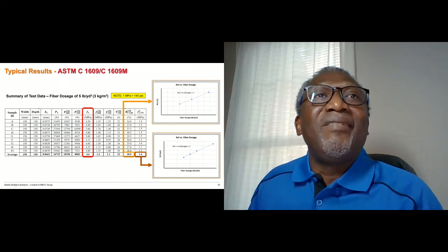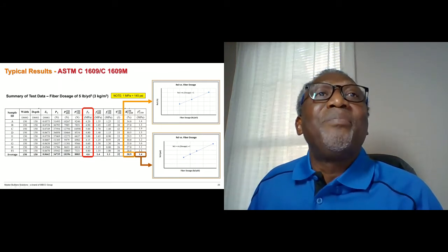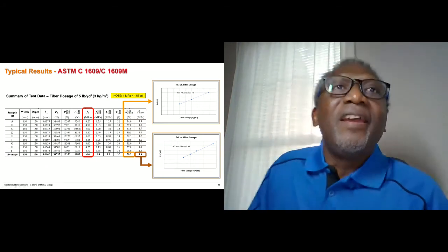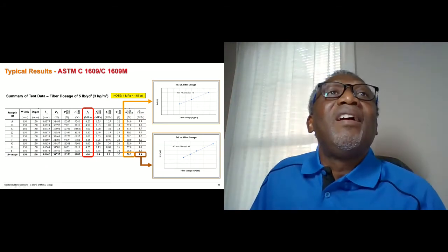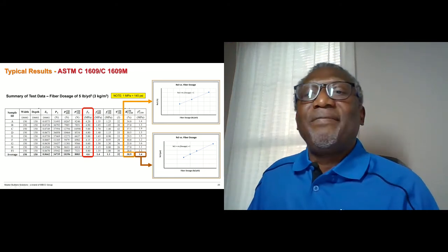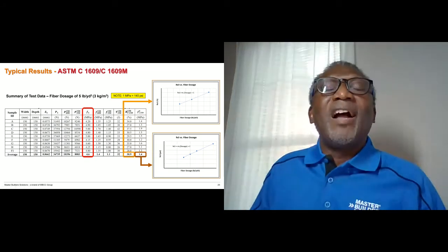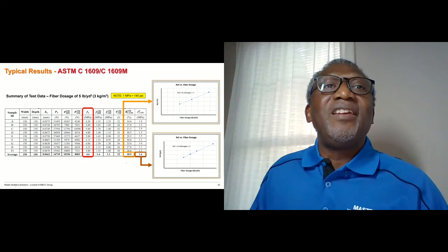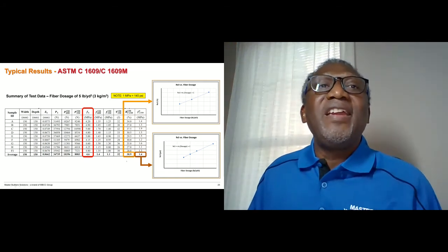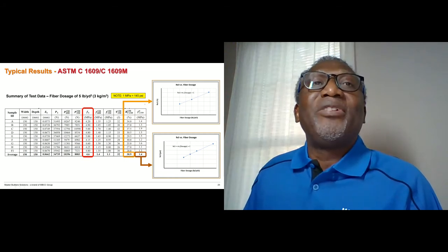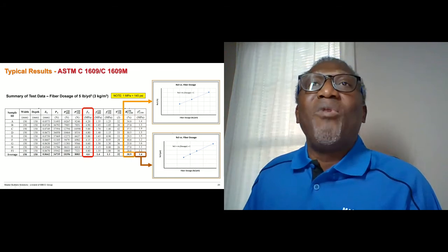And then the last two columns represent two parameters, the fe3 150 and the R e3 150. The fe3 150 is the equivalent flexural strength of the concrete, and the Re3 150, which we also call the Re3, represents the equivalent flexural strength ratio for the concrete, which is essentially your fe3 divided by your F1.